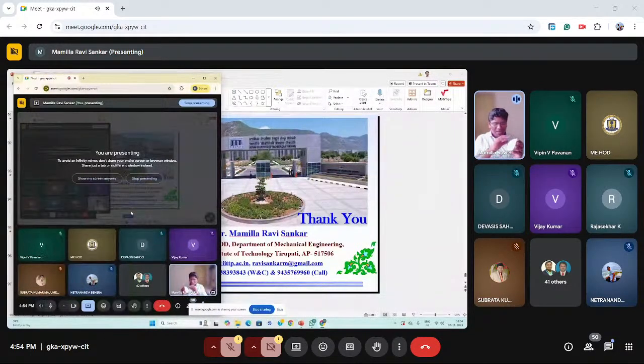So, what are the methods to find the adhesion strength during the coating process? Adhesion strength you can do using a scratch test basically. Assume that you have this particular surface and you just coat on the surface. Assume that in my study you have titanium, and on top of it hydroxyapatite is coated.